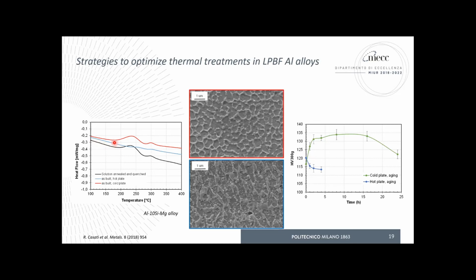And the blue line is for a sample which was produced by keeping the powder at high temperature, the so-called hot plate building strategy. So in some cases, people that print parts preheat the platform and keep the powder hot during processing to remove residual stresses. In this case, the temperature was 160 degrees, which is exactly the aging temperature. And the corresponding DSC curve of the part produced by this process is a very flat blue curve. So no chance of having any kind of aging, we lose the ability of having aging.